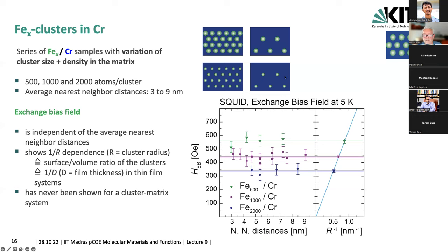Or here you have a different size. And then we measured the exchange bias field, in the same way I just described for the thin film. And you can plot it here as a function of these nearest neighbor distances, which are calculated from an average distribution of equal sized clusters in the matrix. And what you see is that there is a dependence on the cluster size, but this is also expected. And then there is not much of a difference for the different volume fractions or distances between the clusters. And if you plot that over here as a function of the inverse radius of the clusters, you see there's also, again, this dependence. But this is very similar to what you would observe if you take, instead of the radius, the thickness of these multilayered films. So that's what I said before.